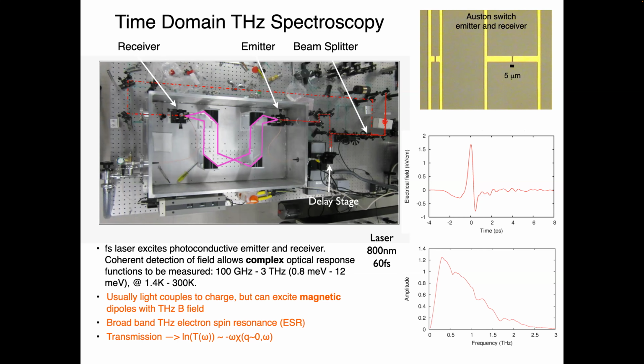We put a sample, let's say right there, and we measure how much radiation gets through, say the amplitude of the electric field, and we measure the phase shift. And so we measure two things, and from the two things we measure, we can get the complex response. We want to measure the complex conductivity, let's say, or some complex response function, whatever that might happen to be. We do lots of different experiments with this.